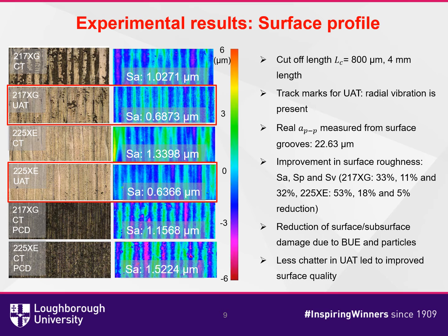Surface roughness values of Sa, Sp, and Sv were all reduced by 33%, 11%, and 32% respectively for 217xg, and 53%, 18%, and 5% respectively for 225XE. This was due to reduction of surface damage from BUE and particles. Less chattering on UAT surfaces also resulted in improvement of the surface roughness.